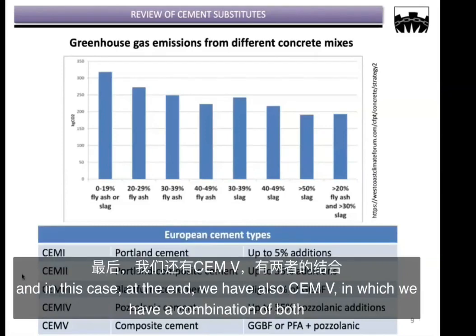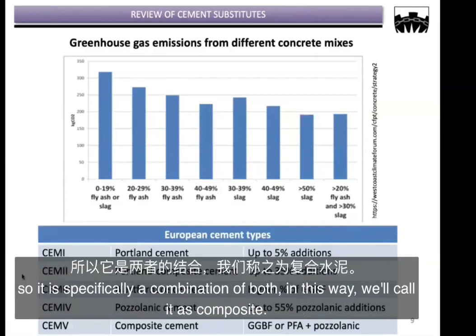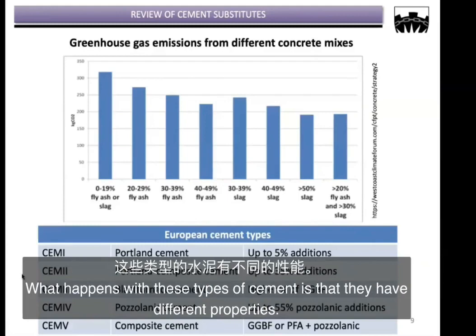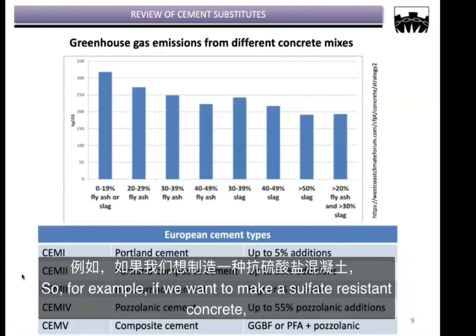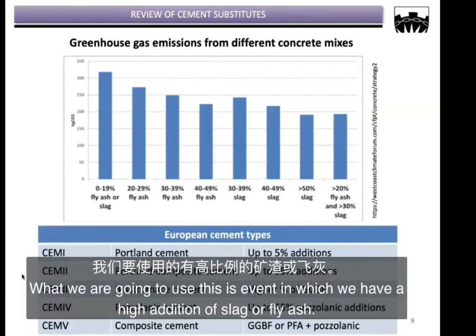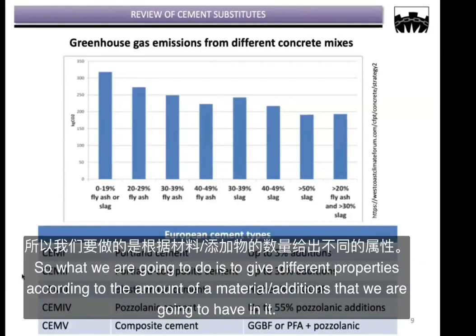And in this case, at the end, we have also a CEM5, in which we have a combination of both, right? So it is specifically a combination of both. That is why we call it composite. What happens with these types of cement is that they have different properties. So for example, if we want to make a sulfate resistant concrete, we are going to use a cement with a high addition of slag or a high addition of fly ash. So we are going to give different properties according to the amount of additions that we are going to have in it.